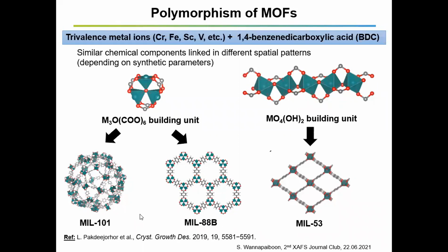So basically there are 2 kinds of this. We have the mu4O, mu3O clusters like this, forming cage structures, which are called MIL-101 and MIL-88B, depending on the orientation of the cluster or the topologies formed at the ends. And if that kind of cluster is changed into a one-dimensional chain like this, it can also form another kind of MOF, called MIL-53, which combines with the 1D chain channel that goes through the structure like this and forms the diamondoid porous frameworks of MIL-53.